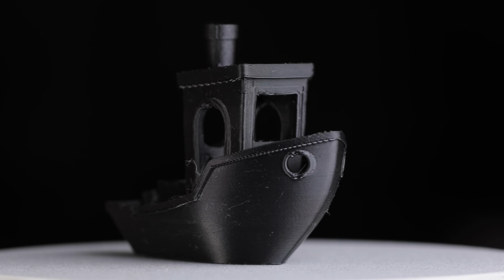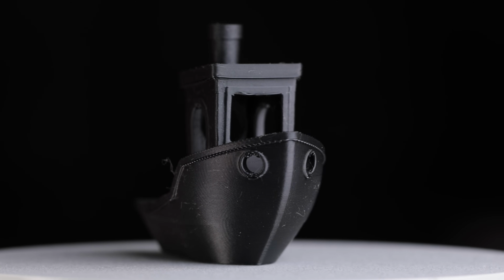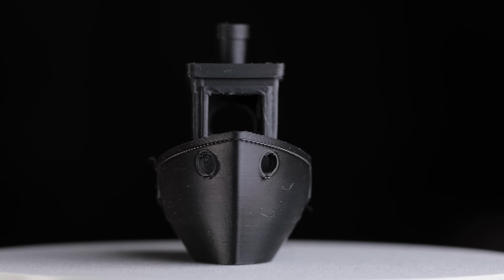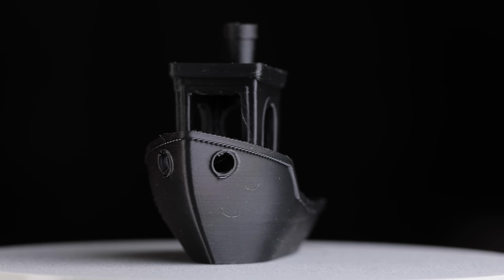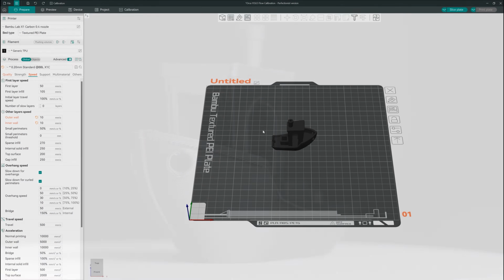After 2 hours and 25 minutes, look at this. These 2 changes made a huge difference. The boat looks amazing. Next up, we are running a flow calibration test. This test checks whether we need to adjust the flow rate for the filament.